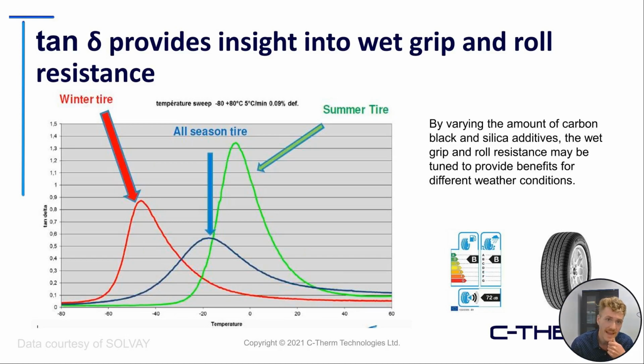By tuning the additives in these tires, we're able to change where the wet grip will occur. So tuning it to have a lower wet grip for winter tires, or more of a plateau in the middle for an all season, or even a higher wet grip for a summer tire. And all of these different formulations are able to be played with by measuring tan delta over a temperature scan, providing mostly a tuned tire for each of the weather events that you're experiencing.